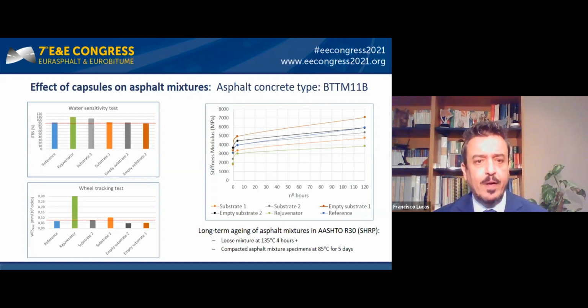We have taken a reference standard mix without rejuvenators, and subsequently, we have considered another mix which contains the same amount of rejuvenator in green color as the substrates, but incorporated directly into the bitumen. In most of the sample tests, both the water sensitivity test and the wheel tracking test fell within the Spanish specification. Likewise, we want to see the behavior of the capsules without a rejuvenator.